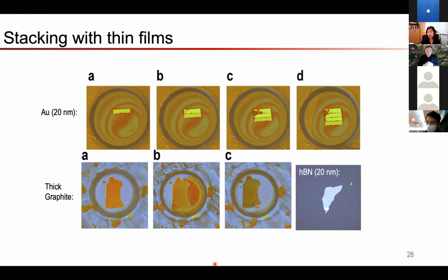But what's fascinating but also challenging about this field is that the precise physics often does vary from device to device. But we think that this is not necessarily due to variation in, let's say, the exact lateral registry between atoms, but it's more like, for instance, disorder in the twist angle across the device. And so this is something that we are seeking to actively control or to improve our quality. We want to actually benchmark that using this technique.